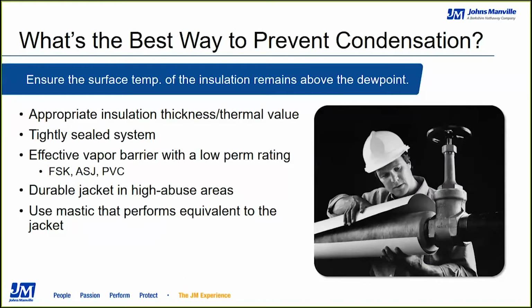from occurring. Typically, that can be done with vapor barriers like FSK jacketing on duct wrap, for instance, or spin glass boards. Could be an ASJ facing or an all-service jacket, like can be found on our Microlok pipe insulation or on the spin glass board. And then PVC can be a low perm vapor barrier. And perm rating is how a vapor barrier is evaluated. Typically, you want to have a perm rating below 1, and most JM insulations have a perm rating of 0.02. So quite good at being a vapor barrier.